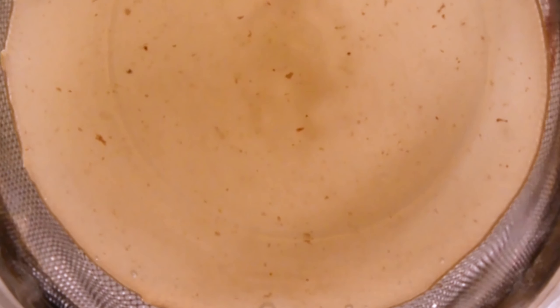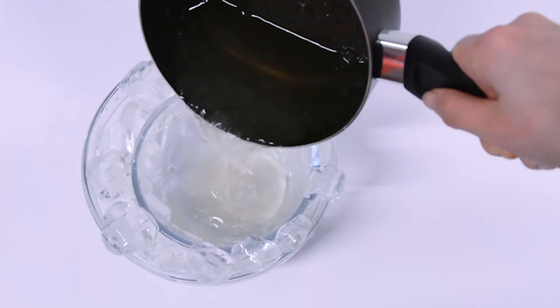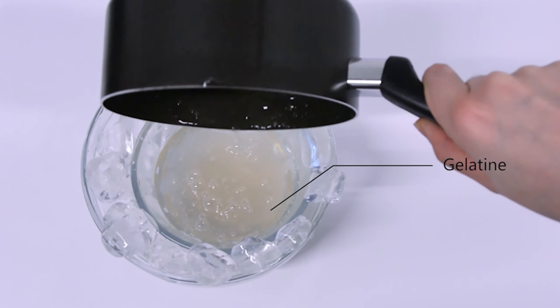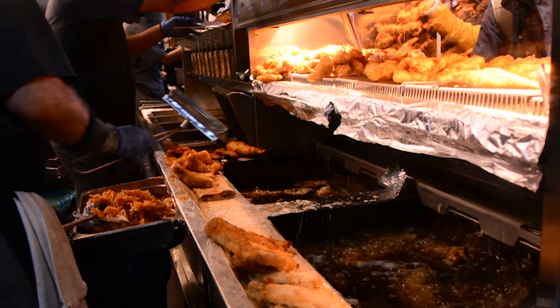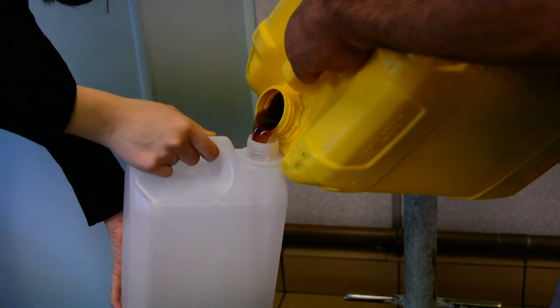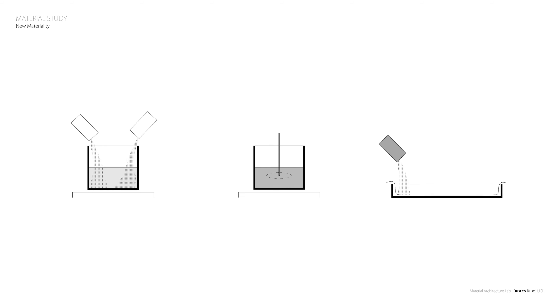Gelatin is extracted from meat waste to develop the protein-based material. To test this process, we firstly collected discarded pork skin and beef bones from a butcher shop and then extracted the gelatin by boiling. We then recovered waste vegetable oil from a fried fish restaurant in order to produce glycerine. We mixed the gelatin solution and the glycerine in specific quantities in order to test iterations of the new material. The mixture dehydrates and hardens according to the shape of the mold, forming a light yellow translucent solid.